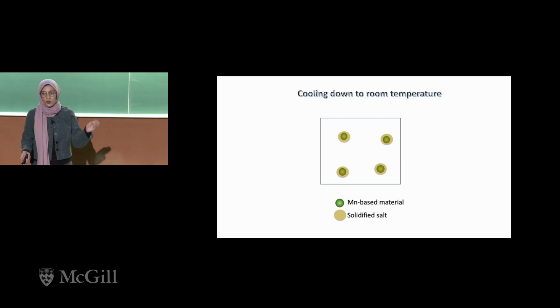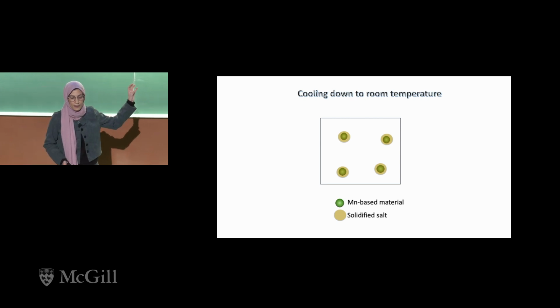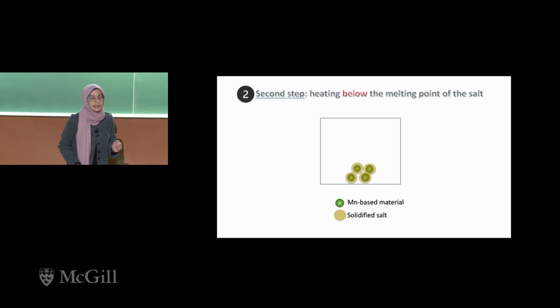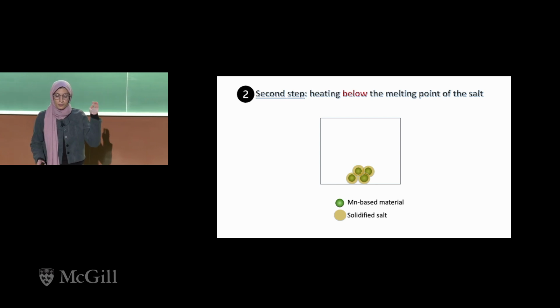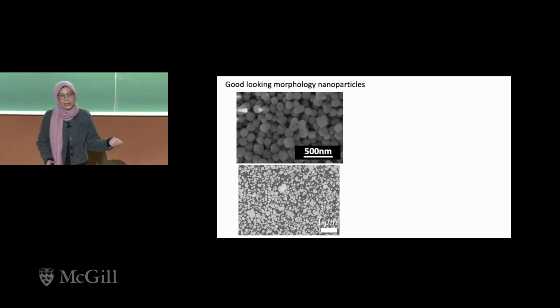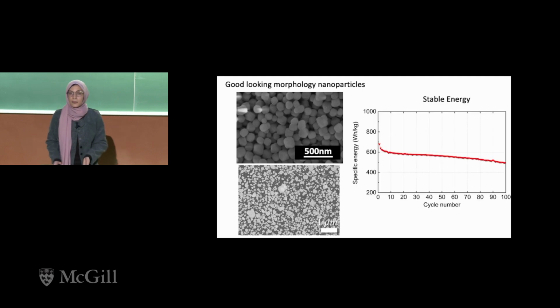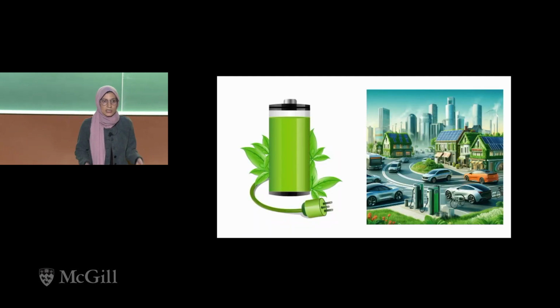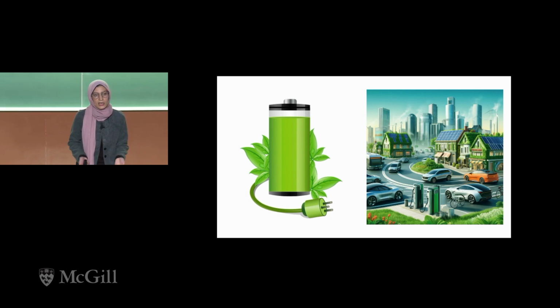After cooling down, the salt will solidify surrounding these small particles. So next step, we will apply another heat treatment. Here, we will heat the product of the first step, but this time below the melting point of the salt, in order to improve any incomplete reaction, while the solidified salt prevents any further particle growth. After washing away the salt in water, we obtain small nanoparticle manganese-based material with uniform distribution in the electrode film and stable energy. So I'm confident that with my project, we will be paving the way for sustainable batteries and a sustainable future. Thank you.